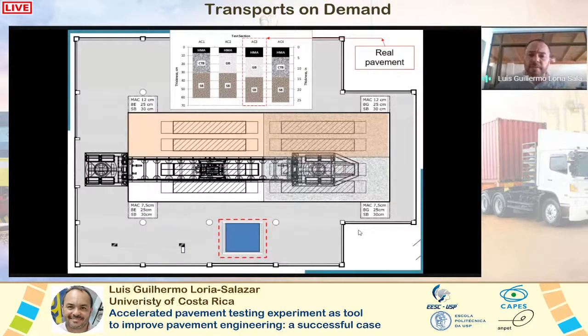This is the initial experiment we developed at the University of Costa Rica: 4 pavement structures with the typical conditions for Costa Rican pavements, 2 thin layers of 7.5 centimeters, and 2 thick layers, in our case 12 centimeters. These are test tracks AC3 and AC4.